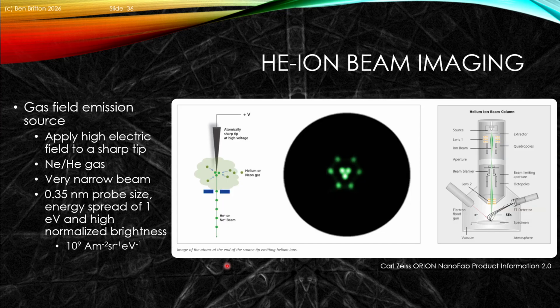In addition to the two sources that we've seen so far, we can also do something clever where we can use field emission. So we can produce an atomically sharp tip. If we apply a high voltage to this tip and then have a helium or neon gas, those neon gas atoms will then form a trimer on the surface of the tip, and then we can effectively eject that trimer and bring it down as ions through the column, and that produces a beautifully narrow beam.